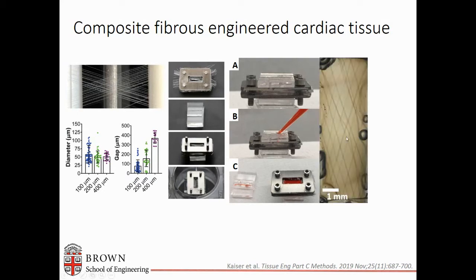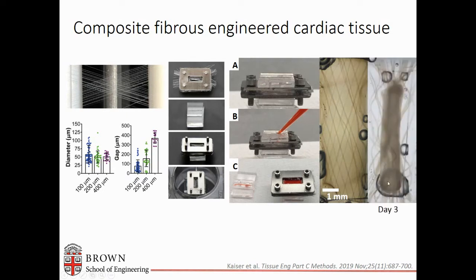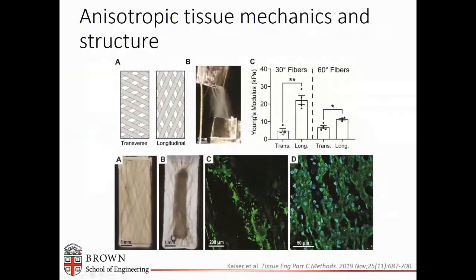And upon hydration, you can see some swelling of the fibers, and then after 3 days, the cells will compact into a tissue. We did mechanics in the transverse and longitudinal direction on these fibers, and what we found was that we could get a different stiffness based on the fiber angle, here showing 30 degree and 60 degree fibers. And the ratio of these stiffnesses actually captures that found in the native myocardium.